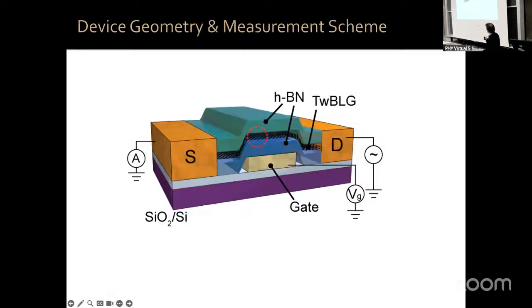Okay, so then we do standard nanofabrication that thousands of groups around the world can do, where we take the twisted bilayer graphene, encapsulated in top and bottom boron nitride, so that we have a nice sandwich - the cheese is the twisted bilayer graphene - and its properties can be maintained, very pristine. We contact with source and drain electrodes so that we can apply a voltage and measure a current that circulates through this device. And importantly, we have also a metallic electrode called a gate electrode.